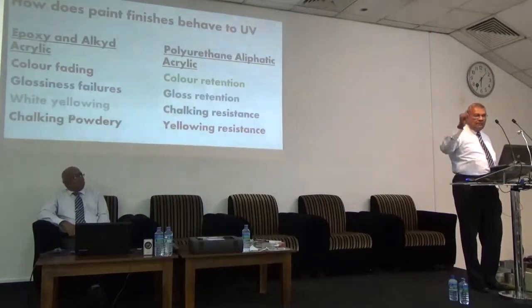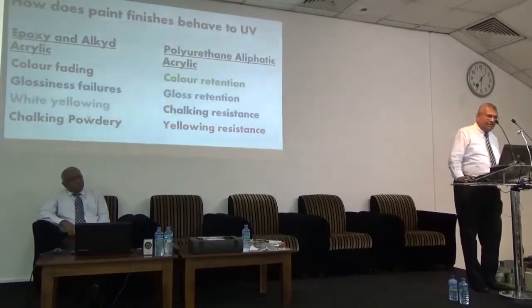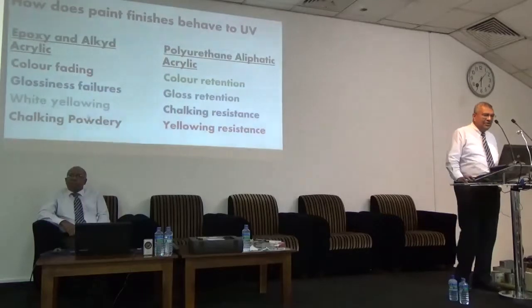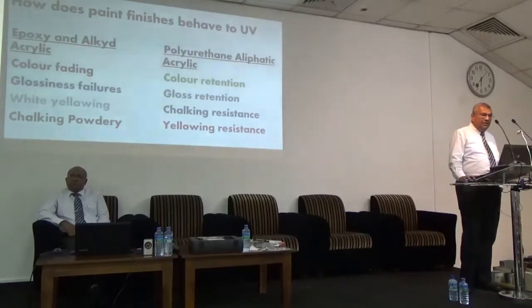So now those paints are one pack, those are not giving any UV protection. There is aromatic. So now aliphatic acrylic polyurethanes, if you apply the paint, you have a prolonged color retention, prolonged gloss retention, chalking resistance.